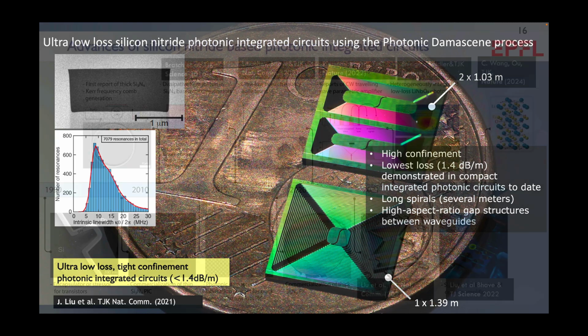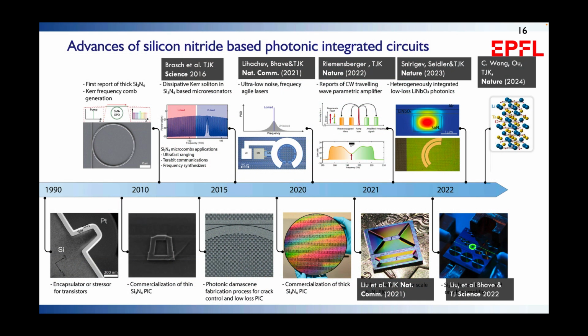in this presentation. So in a nutshell, starting, as I said, from the use of silicon nitride in the CMOS as a stressor layer, we can now actually use silicon nitride to generate optical frequency combs. The material has been commercialized, transferred also to foundry. And I'd like to highlight in this presentation 3 applications of this material, in particular making very low noise laser, making chip scale optical frequency combs, and also optical amplifiers using rare earth ions. And so this is really opening up many new applications.